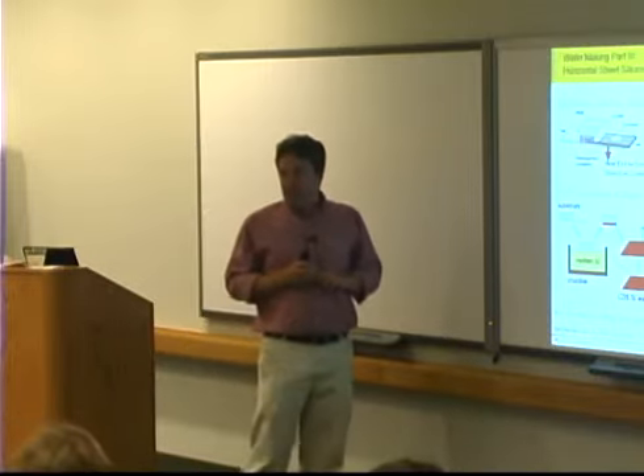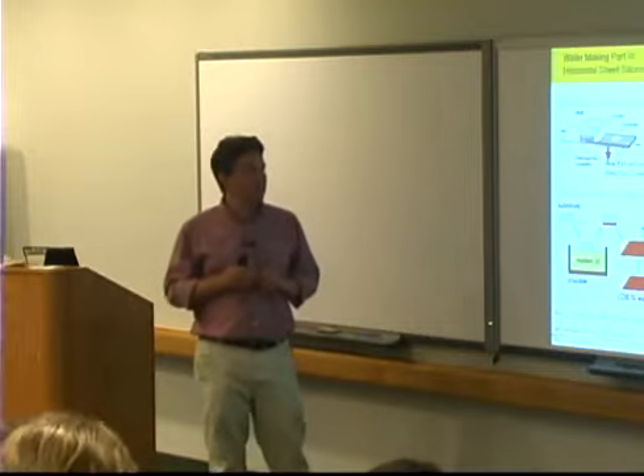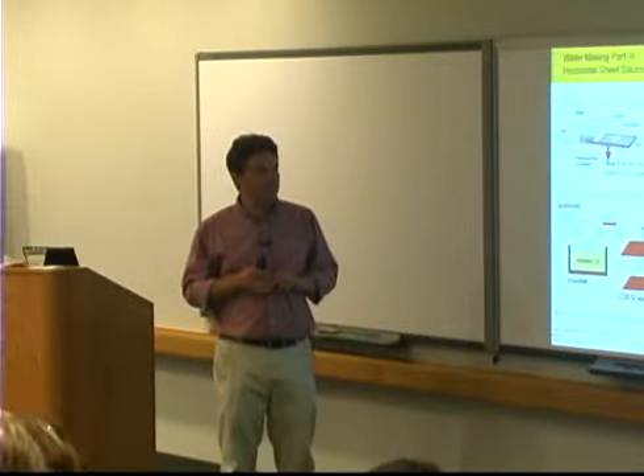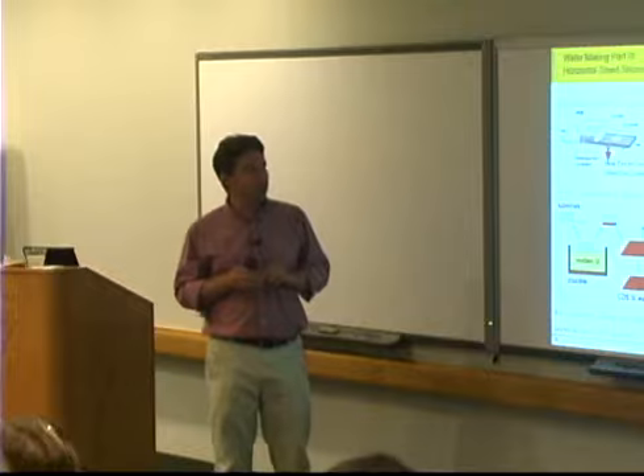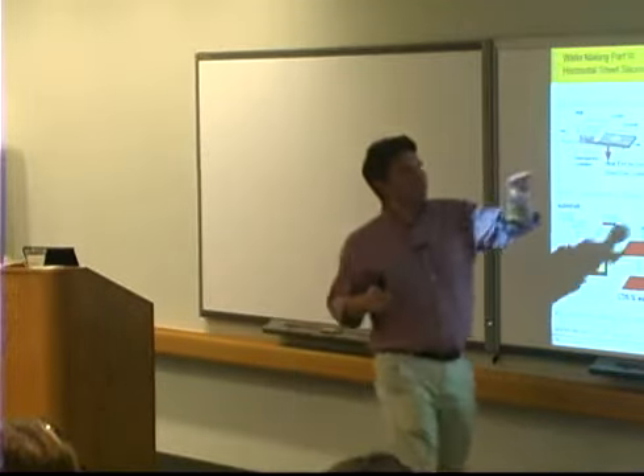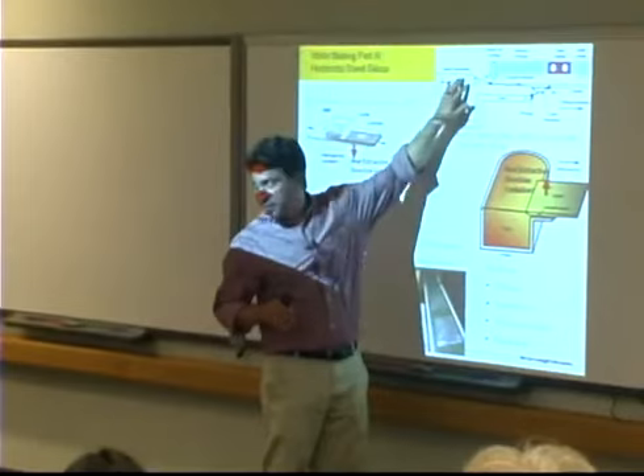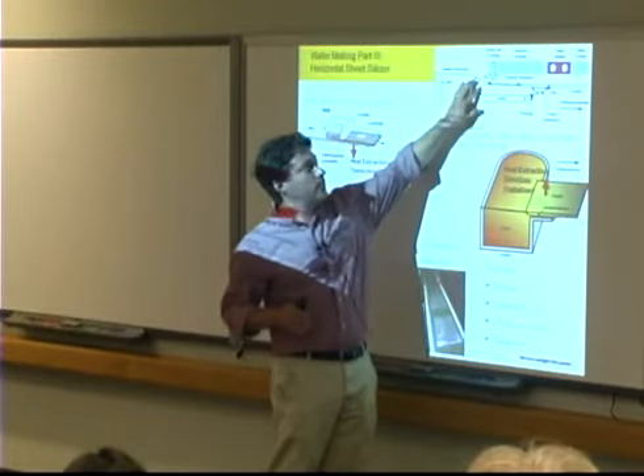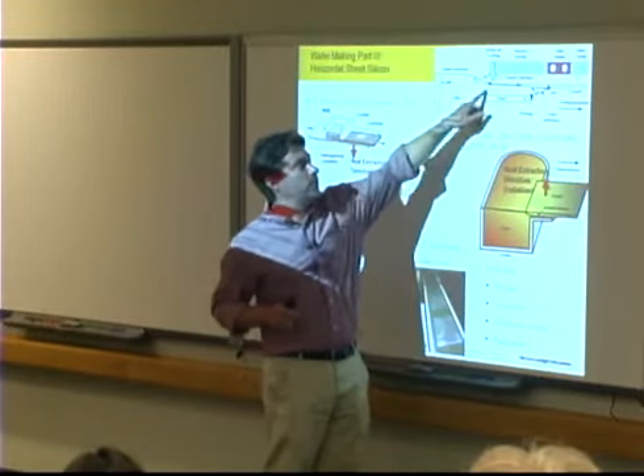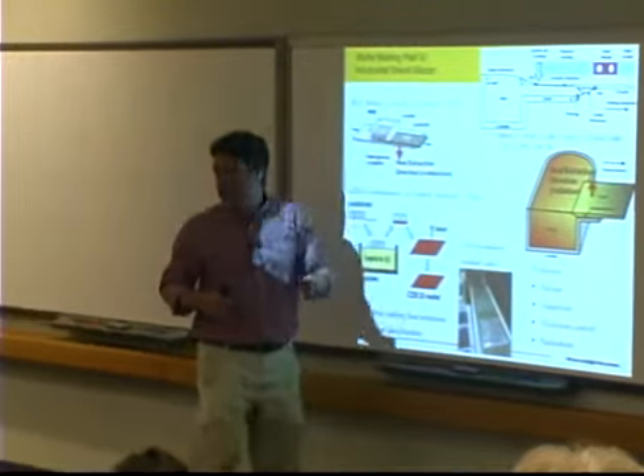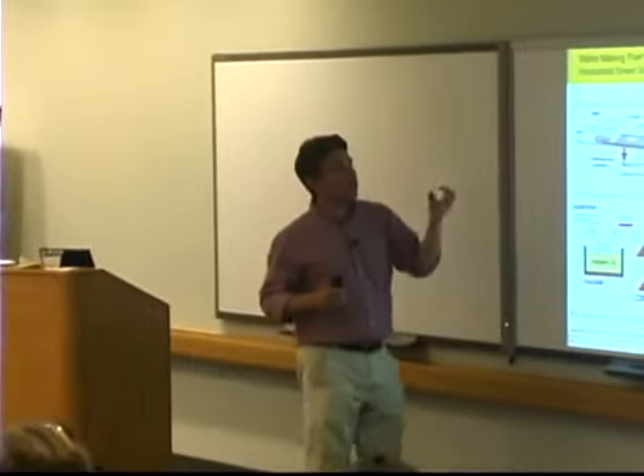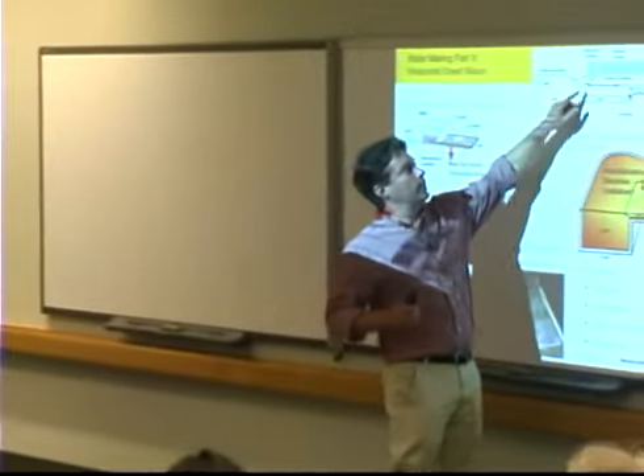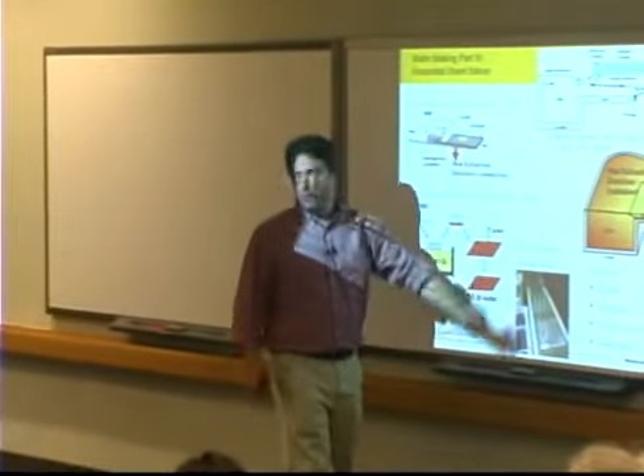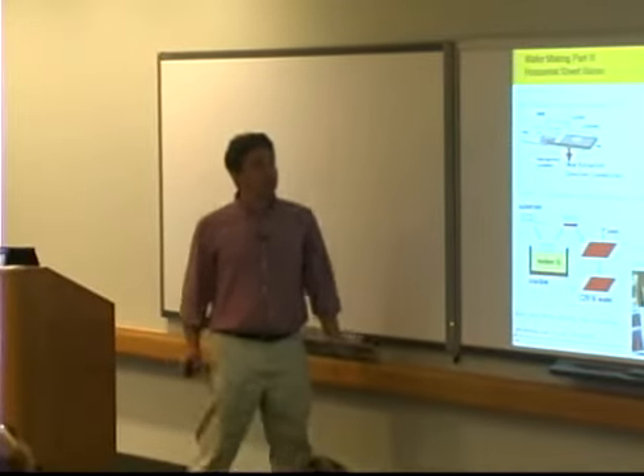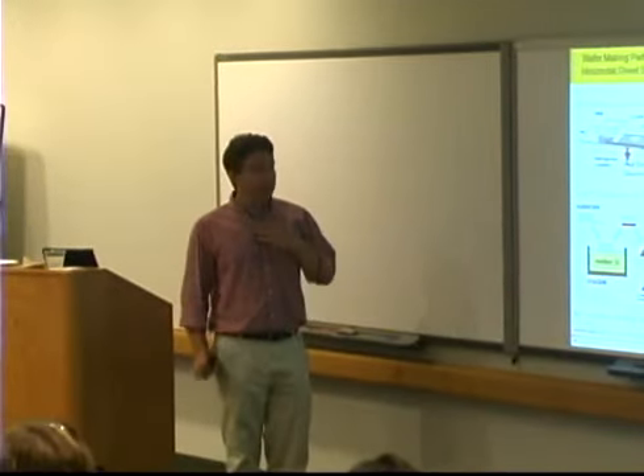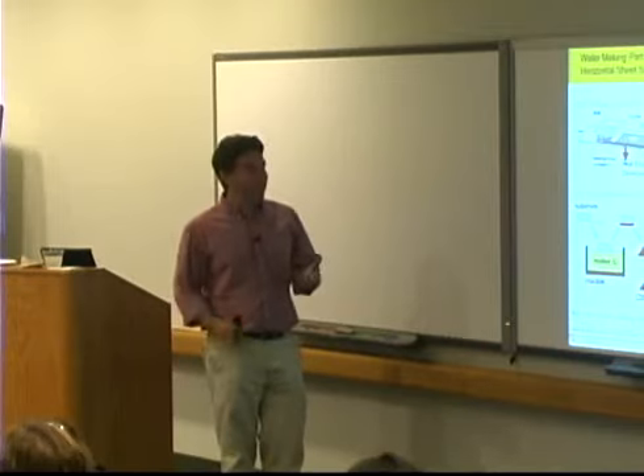We looked into that, and we did a couple different attempts, and in every case, it wasn't confined enough, and it would end up cooling the melt up here, and then once this melt gets cooled, then you start getting dendrites growing out into the melt, because there's essentially a well of supercooling out here, and the silicon just jumps right into that. So I'm not saying it can't be done, but I wasn't able to do it, at least in the year that I spent trying.